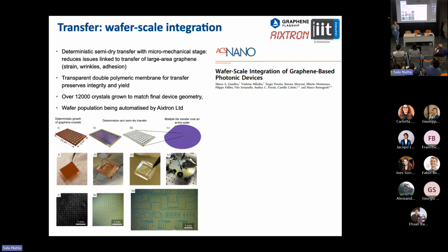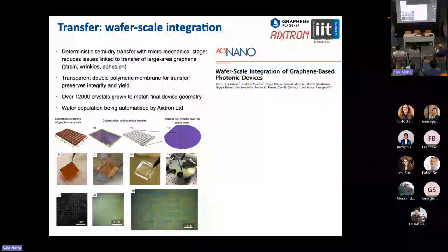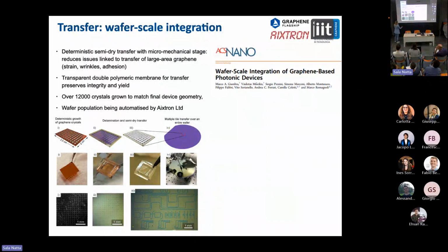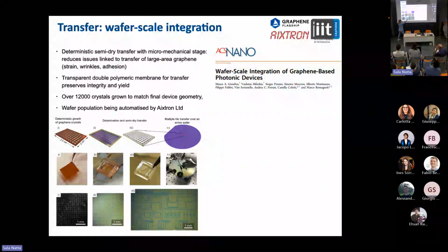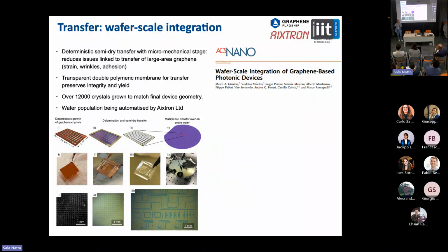So we typically do not grow a 6-inch wafer of graphene because it's too large. You would need a temperature homogeneity very, very fine over too large an area. That's something that the tools don't do. So we typically grow something that is 2 or 3 centimeters by 3 centimeters, in arrays for example, and then we populate an entire wafer with multiple dry transfers. So we just do a kind of stamping technique, right? And we automatized with Aixtron a stamping tool that is capable of just doing that.